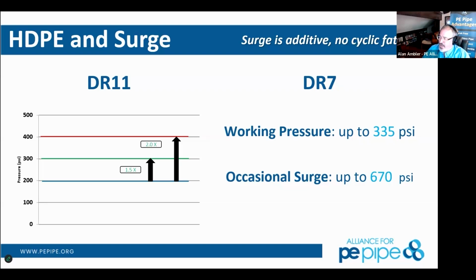So surge is calculated differently for the three main pipe material types at AWWA that we look at and often compete in smaller diameters. That's PVC, HDPE, and ductile iron. High density polyethylene can take a 1.5 times surge for recurring surge, and that happens to be 55 cycles per day, or 2 times that for occasional surge, which is that 6 times a day thereabouts.